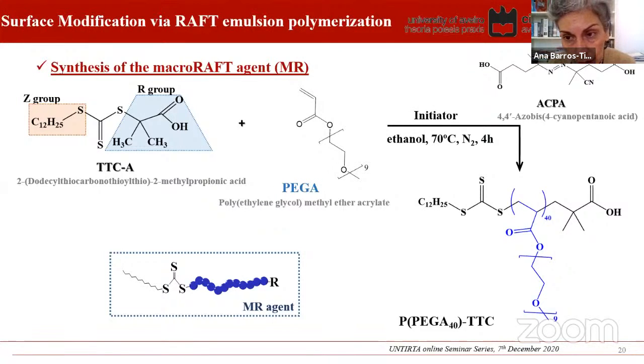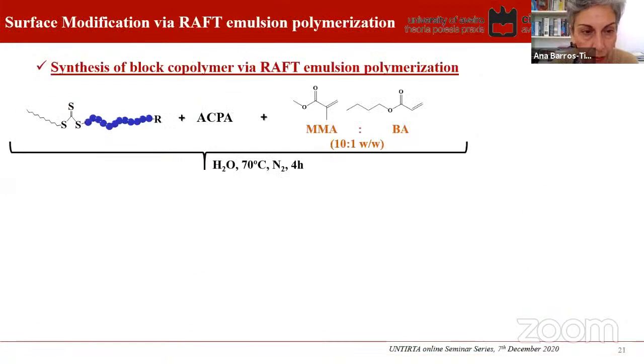The polymer that we grew was based on ethylene glycol methyl ether acrylate. So we used also this initiator ACPA, and the reaction medium was ethanol, all this to prepare the macro RAFT agent based on what we call PEGA, so this polyethylene glycol methyl ether acrylate, because it is a well-known type of polymer for use in biological tests, and also has some responsiveness to temperature, which can be further explored if one wants.